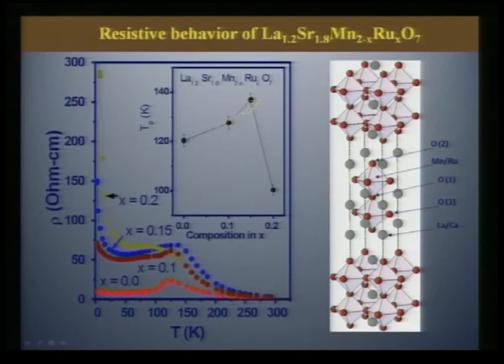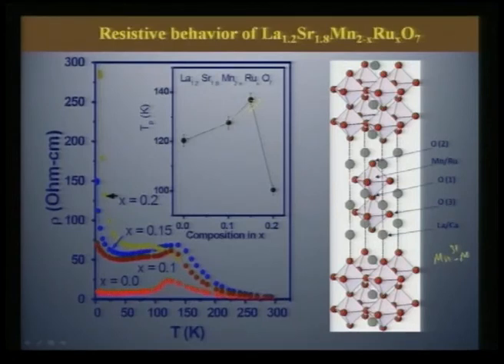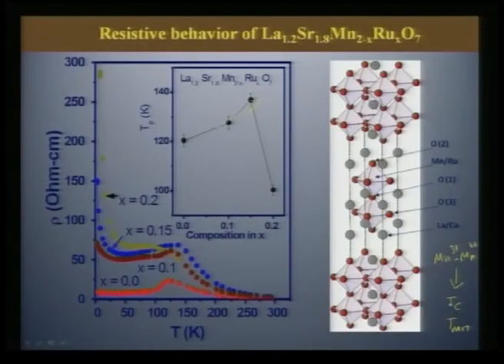So, what really happens in this case? Why does ruthenium have to increase the ferromagnetic transition? As I told you, manganese 3 plus, manganese 4 plus is very intricate. When you substitute, it should actually kill ferromagnetism and metallicity, whereas in this case, it is on the reverse gear. It is increasing the metal insulator transition and it is increasing the ferromagnetic transition. Therefore, there should be something unusual happening with ruthenium, especially in these layered perovskites, and that is what we will see in the next few slides.